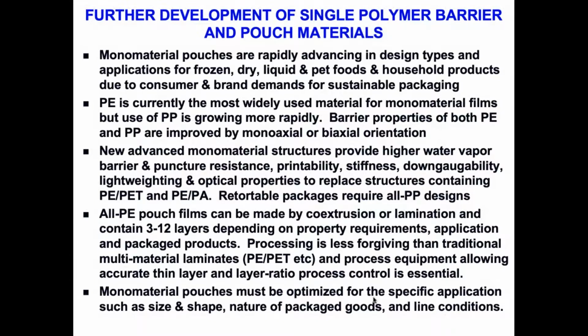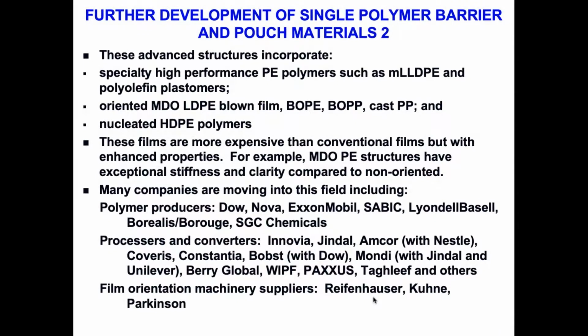The all polyethylene pouches can be made by co-extrusion or lamination. They contain multiple layers, between 3 and 12 layers, depending on the application and the property requirements. It's important, though, to recognize that the processing is a little more tricky than using traditional multi-material laminates, and you need processing equipment which allows for accurate thin layer and layer ratio control. And the monomaterial pouches generally have to be optimized for specific applications and the nature of the packaged goods and the line conditions. So these advanced structures incorporate specialty high-performance PE polymers, such as metallocene LLDPE and polyolefin plastomers.